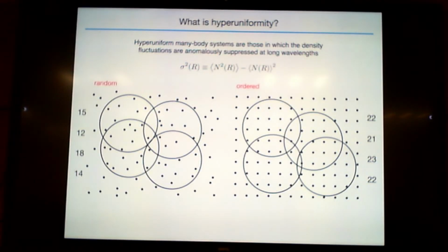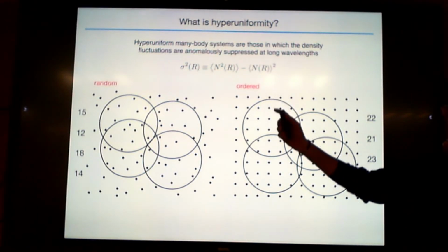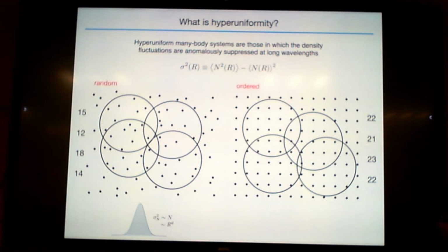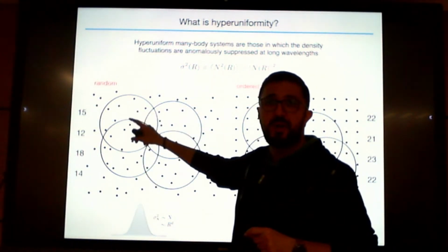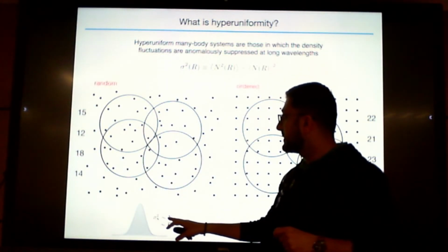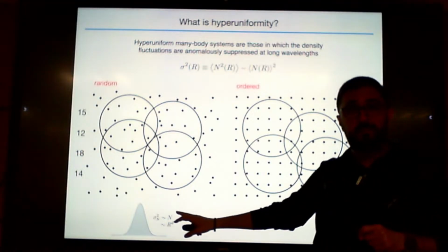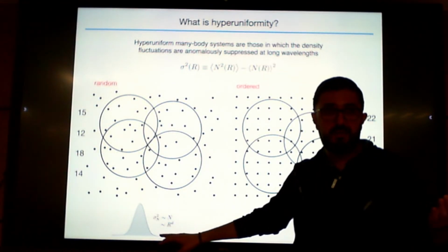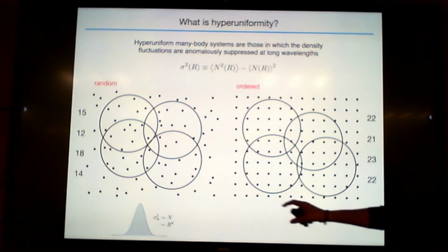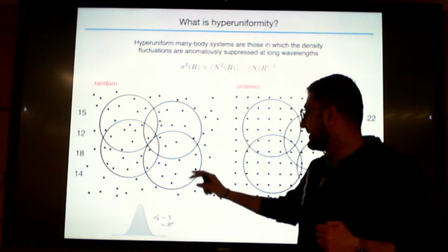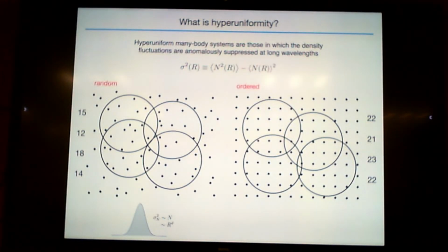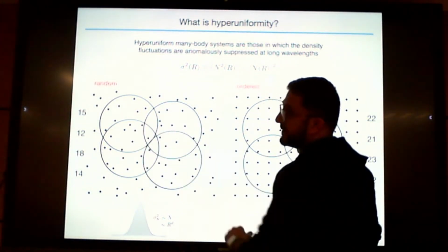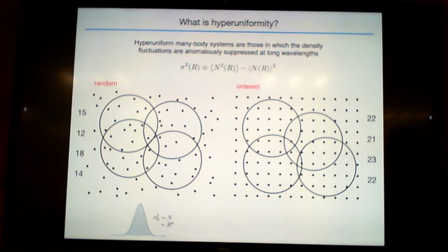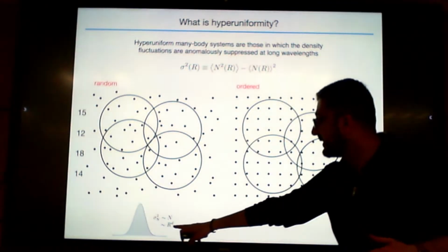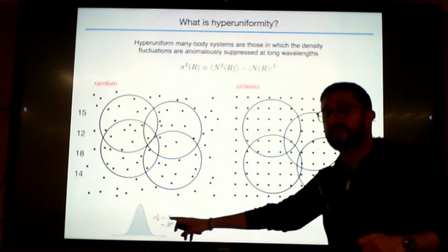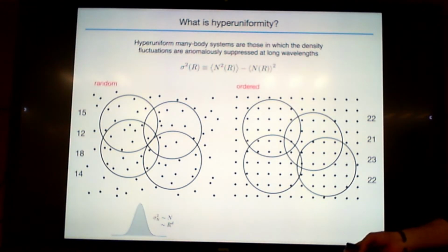Now, what I realize, if I calculate the sigma square, the number variance, is that the number variance in a system where I just put these particles randomly grows actually with n, which is proportional to the volume, or the area of the circle. So when I put a window and I keep changing the position of the window and I calculate the number variance, the variance grows. I'm not talking here about the coefficient, I'm talking about the proportionality, right? The variance grows as r to the power of the dimension of the system d, in this case 2.